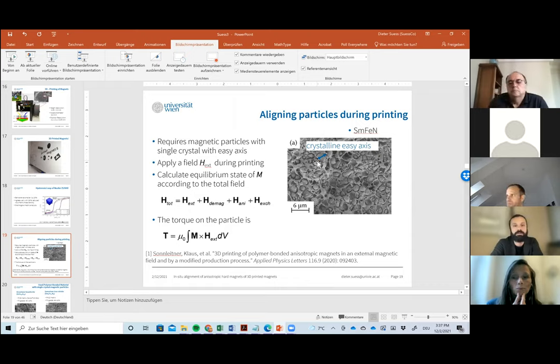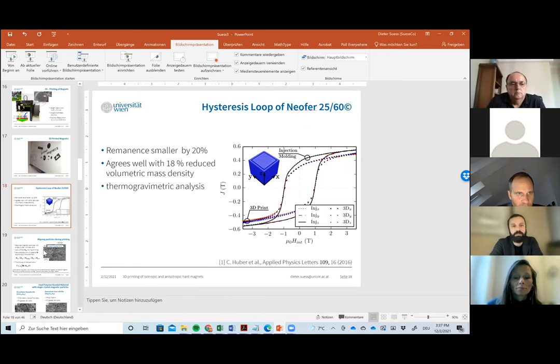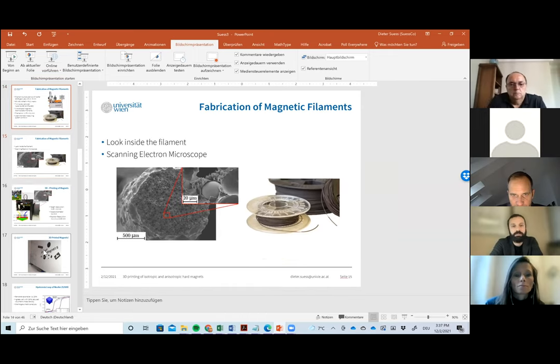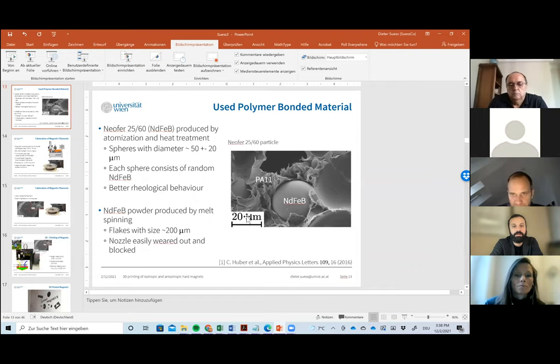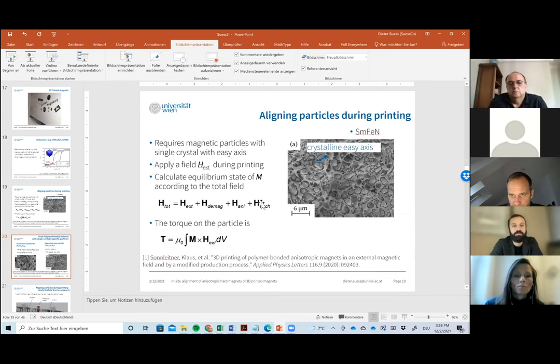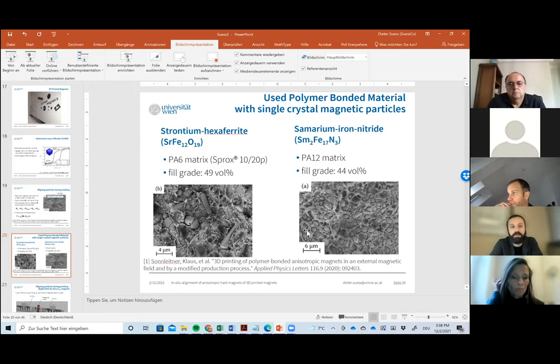Okay. But you never tested with particles with different sizes? The size of the particles was indeed almost similar. If they are much larger, you can't print it for sure. But these particles were significantly larger. The magnetic powder is about 50 micrometers. The samarium iron nitride particles are significantly smaller, one order of magnitude smaller. But the resolution of the printed magnet is similar. Nevertheless, with the samarium iron nitride, I think due to the smaller diameter of the particles, the filament has better properties. It's not so fragile and more elastic. So this samarium iron nitride was a very nice filament.